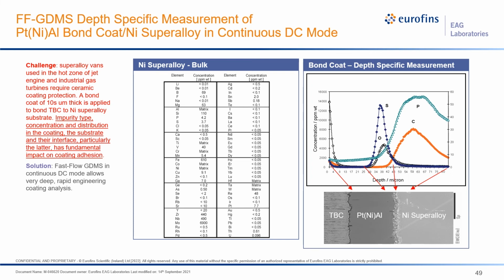Superalloy vanes used in the hot zone of jet engines and industrial gas turbines generally require ceramic coating protection. A bond coat of tens of micrometers thick is applied to bond the TBC to nickel superalloy substrates. The impurity type, the concentration, and their distribution in the coating, the substrate, and the interface, particularly the latter, have a fundamental impact on the coating adhesion.